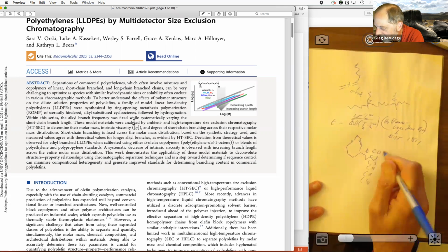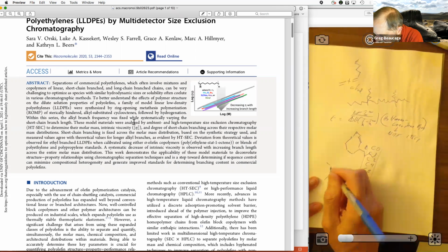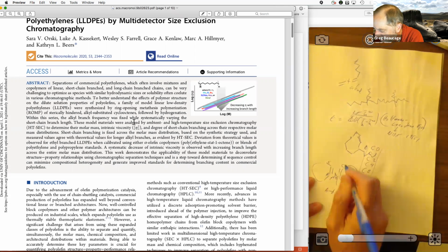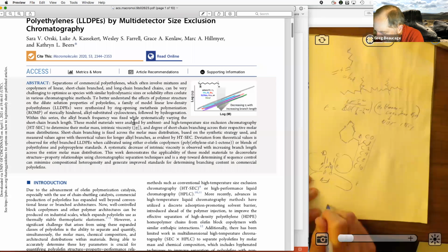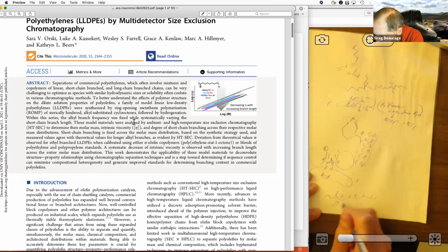So they did all these different series, and then they did metathesis polymerization, which is kind of switching partners for double bonds. So say you have this cyclic, you have another cyclic pulls up, the catalyst site is here, and then it will switch the partners. So partner A, B, C, D. So instead of AC, it goes AB, and then CD match up, and then the double bond remains. So then you have this big cyclic that's 16. If you do that enough, you're going to get eventually a linear chain that's got every 8 carbons a side group on it, exactly, right? And then it's got double bonds in it left from the metathesis.